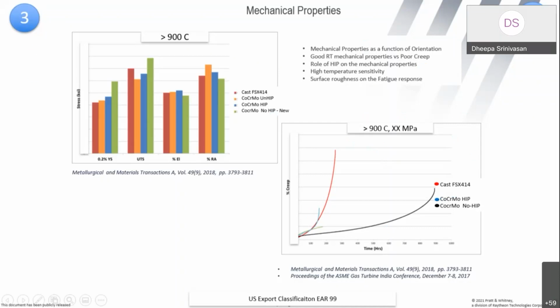So why is this a challenge? This is a challenge because in some cases, as you all know very well, the mechanical properties can be orientation dependent. Modulus can be very low in one direction or orientation. It can be higher than the nominal value in the other orientation or direction. I'm only talking of two orientations at 90 degrees, transverse and longitudinal. However, it depends on the application that you're working on. It's definitely a challenge because typically a thumb rule is that the transverse is always higher in strength as compared to the longitudinal orientation.